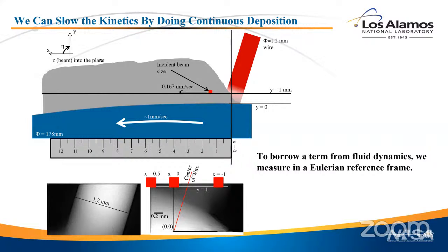That little red dot that I show up there, that's the size of the beam relative. That's kind of drawn to scale. So the wheel is 178 millimeters diameter. That's the blue bottom part. That's the base plate we're depositing onto. The gray stuff on top is the amount of material we're depositing. That's about 3 millimeters tall. And that little red square is the 50 micron beam. That's the amount of material that we're integrating over as we collect the data. That red line is the wire coming in, and it's schematically supposed to show it melting there at the origin.